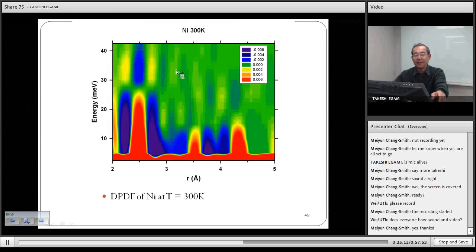Okay? And this is because at this frequency, there's a so-called Van Hove singularity. The phonon frequency becomes, phonon dispersion becomes flat. So I'll not get into details, but here phonons become localized. Okay? These phonons are localized. So DPDF picks up only the localized phonons. You know, propagating phonons are not really seen.